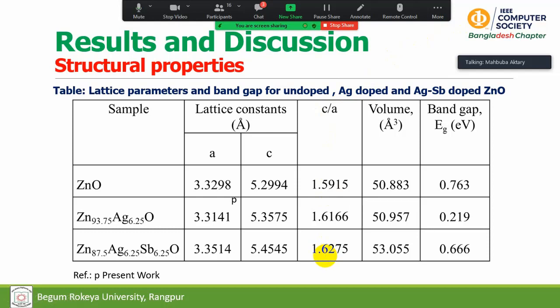And so the evidence of existing the hexagonal phase for both the cases is ensured by this computation. And volume is increased. You can see for doped and undoped element, the undoped element has less volume, and after doping and co-doping, the volume has been increased significantly. And this increment was due to the large dopant size and ionic radii of this silver and antimony.